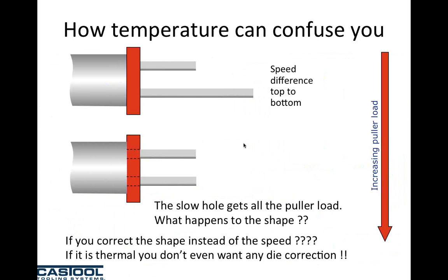We'll talk about the container effect next, but typically the top of the container is hotter than the bottom of the container, anywhere from 50 to 100 degrees. So after you extrude anywhere from 5 to 7 billets, the top of the die will become hotter than the bottom of the die, and again, the flow or your runouts through the top of the die will now be faster. It's very difficult to correct a die for temperature, if not impossible.